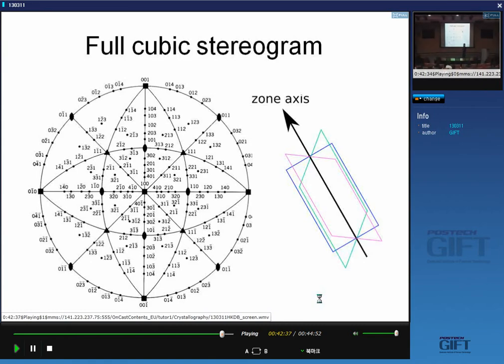So here, for example, this could be the zone axis of all these planes here, because they are all at 90 degrees to this axis. So supposing I put my electron beam along this direction, then I would expect to see diffraction from all these planes, assuming that other things make it possible to get diffraction, because there are certain planes which will not contribute to diffraction because there will be antiphase waves coming through here.